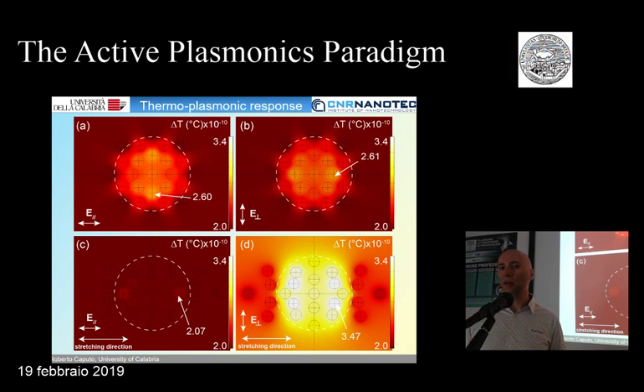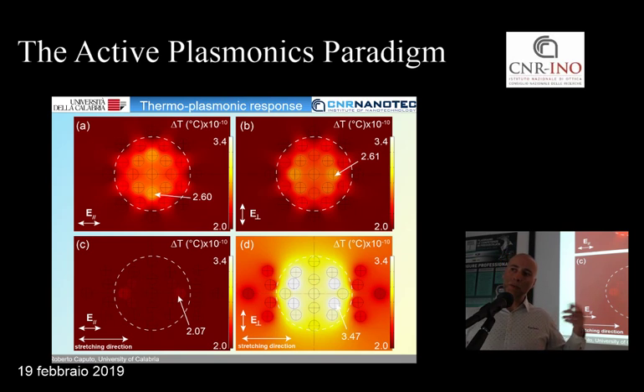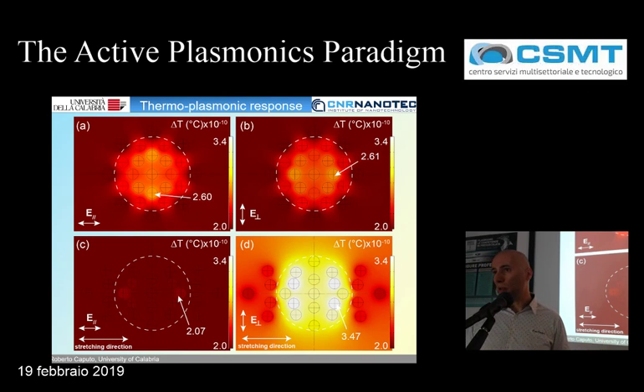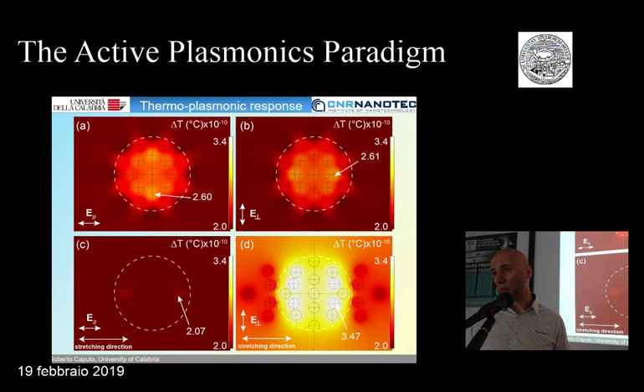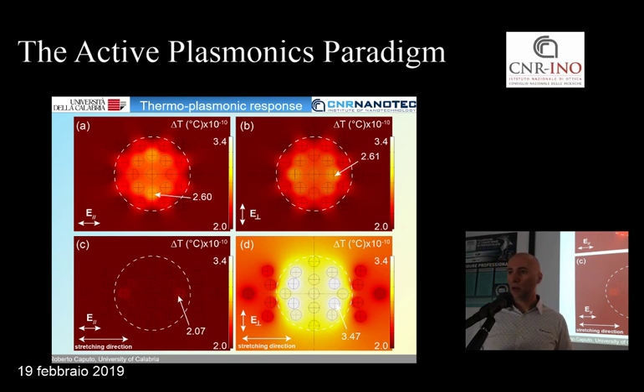We first numerically simulated the plasmonic response in terms of extinction cross sections and calculated the corresponding field maps. And then the obtained field maps are considered in terms of thermal behavior by using a Comsol module for simple heat dissipation by the system. So we just use the heat diffusion equation for calculating this heat response, thermal response of the system. I don't know if I answered your question, but okay, thank you.